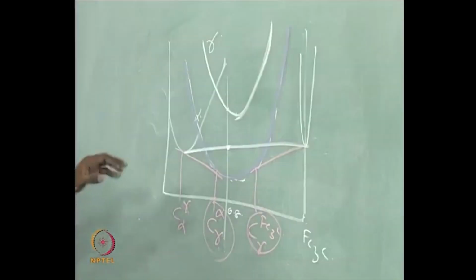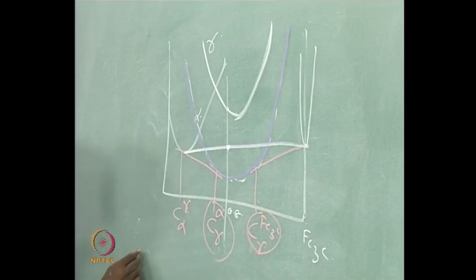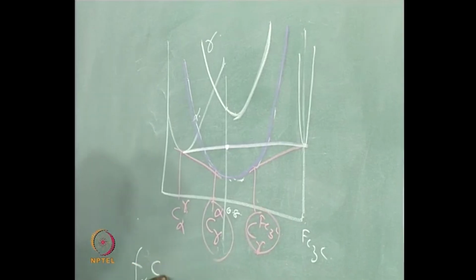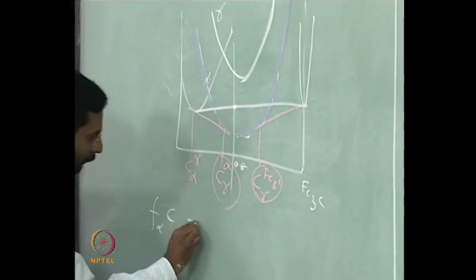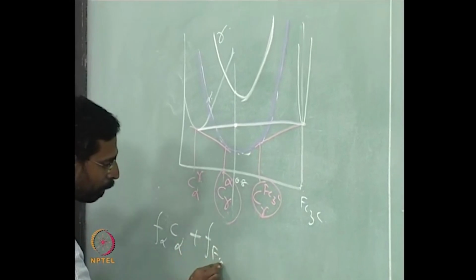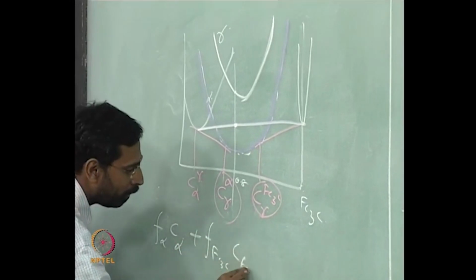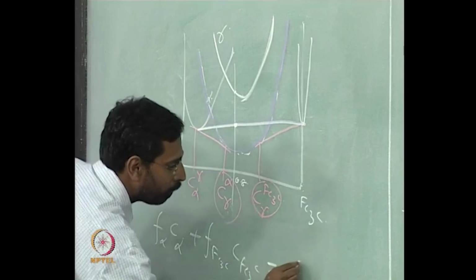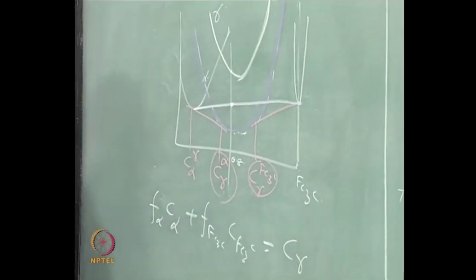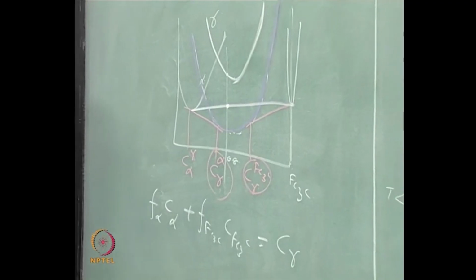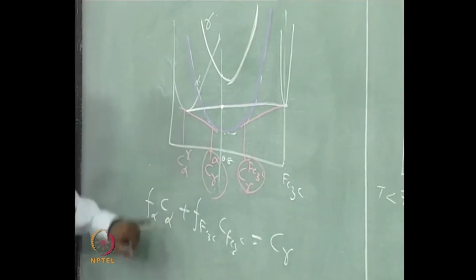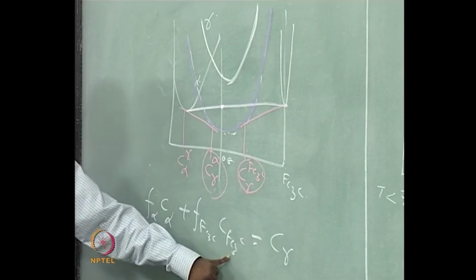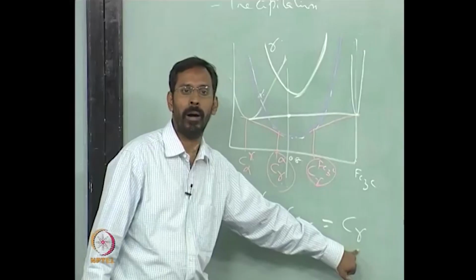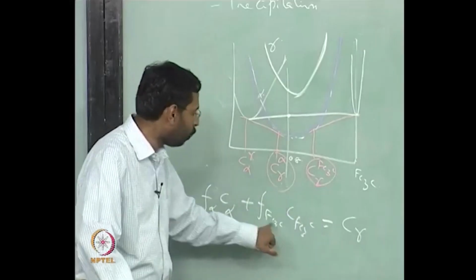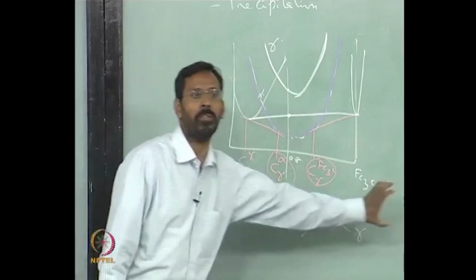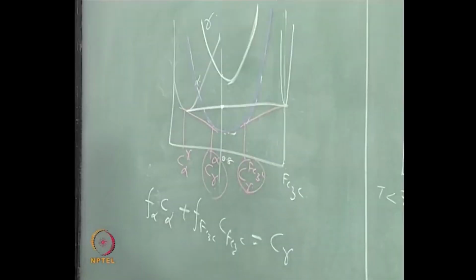Am I right? So, the only way is we can say that the fraction of alpha multiplied by the composition of alpha plus the fraction of cementite multiplied by the composition of cementite should be equal to the composition of gamma. Am I right? This is how it is. So, the composition of alpha and cementite are definitely different from that of gamma, but their fractions will be adjusted in such a way that this mass balance is maintained, and that is what leads you to lever rule.